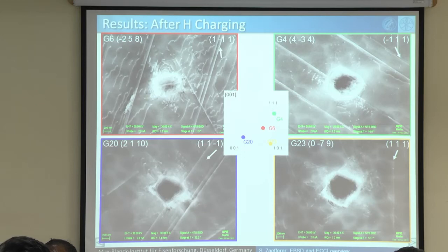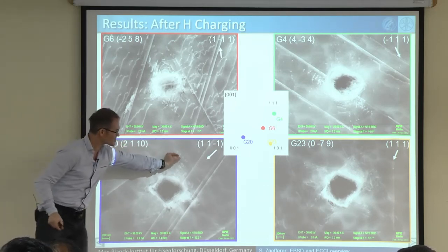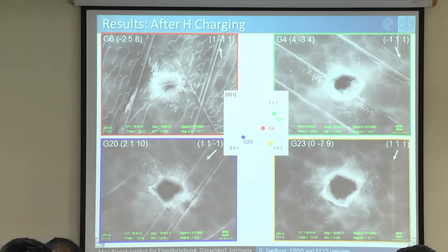And you see here these beautiful dislocations coming out of one source here, and now I can see, is this the same amount of sources activated? Is it the same distance between the dislocations activated? I have all kinds of possibilities to see things which you usually can only see in a TEM, but to see it in an SEM on a bulk material. So that's in principle the power of that technique.